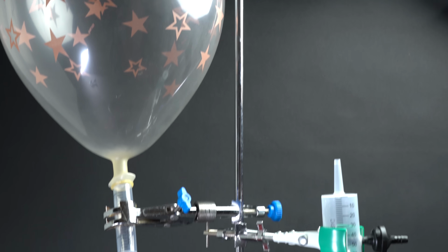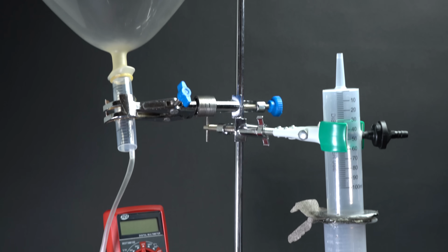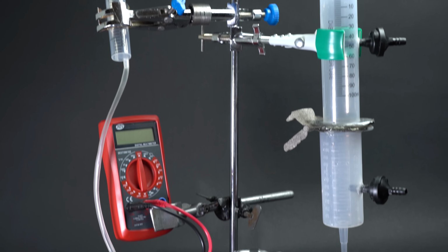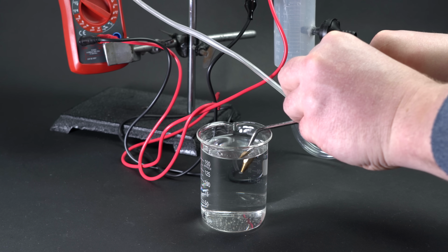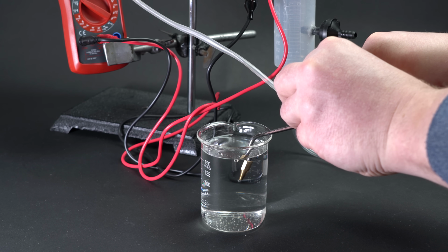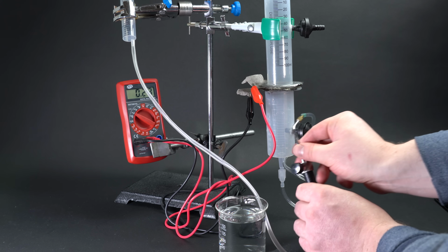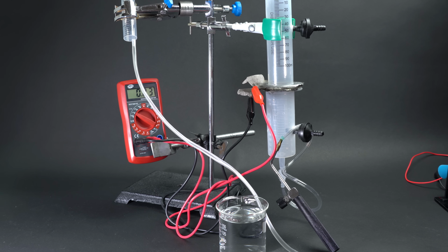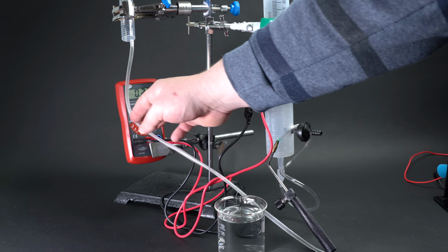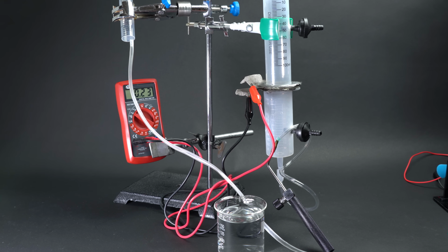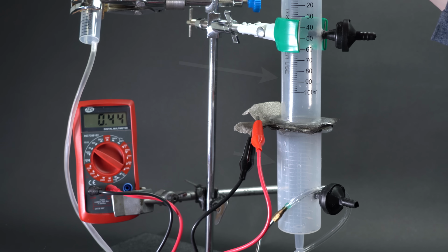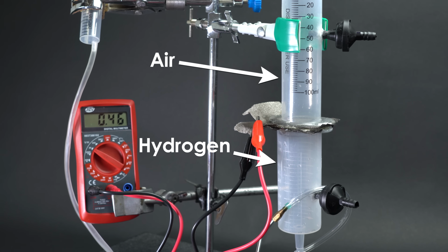For the first test, I am going to use a balloon filled with hydrogen. Then, using a special burner, I began to supply hydrogen into the lower part of my setup, because this gas is lighter than air, and it will be rising up towards the platinum catalyst. The upper syringe case will be filled with just air, 20% of which is oxygen, and I think it will be enough for my experiment.